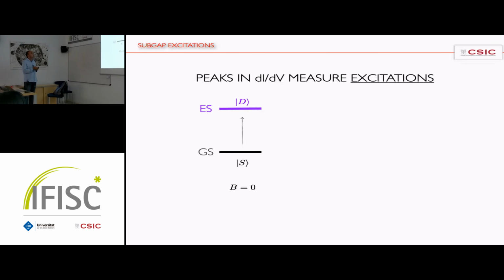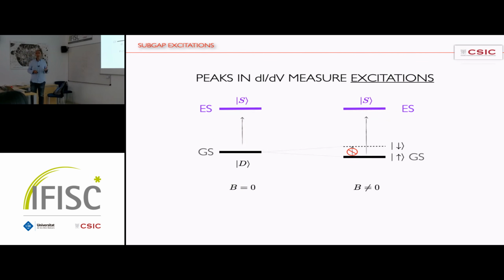Meaning that if I put a magnetic field in a singlet ground state, my excitation, which is a doublet, is going to split due to Zeeman splitting. The line is going to split. But on the contrary, if I am inside the doublet ground state, the line that I measure is an excitation line corresponding to a singlet. And this singlet is not going to split under magnetic field. Okay.